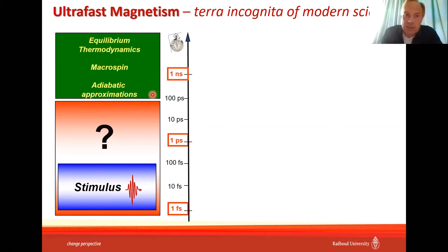Many quantities in magnetism are defined in terms of equilibrium thermodynamics. But if you want to use equilibrium thermodynamics, you have to make sure that the system is at least in a quasi-equilibrium state. So now, if you excite a medium with a very intense, very short stimulus on a timescale of, say, 100 femtoseconds, you bring the medium into a strongly non-equilibrium state. And if you want to use the conventional approach for the description of magnetic phenomena based on thermodynamics, you have to wait at least 100 picoseconds until the process of thermalization is completed. And what we have between 100 femtoseconds and 100 picoseconds, I again like to repeat, is rather unexplored territory in modern science. This is terra incognita of modern science, which we would like to explore.